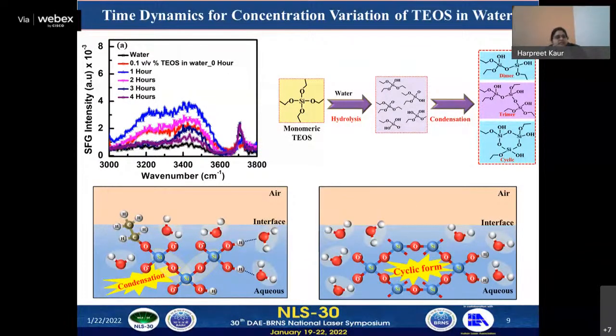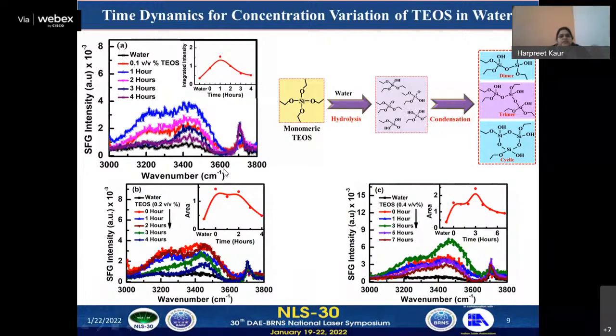And finally, there is formation of cyclic structures and nanoparticles, which is also confirmed from our DLS measurements. So this is the integrated intensity variation with time for this OH stretching region. We have found similar kind of trends for higher concentration as well.